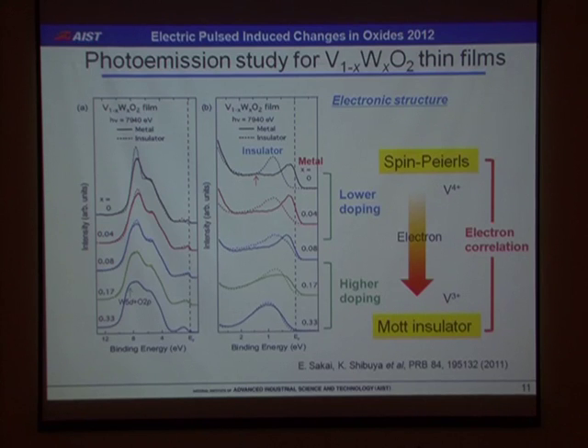And the electronic structure is investigated by photoemission spectroscopy. Here, around 5 electron volts, there is a shoulder, mainly contributed from the hybridization between tungsten 5d and oxygen 2p orbitals. This is the near-EF spectra, and in the lower doping region, the typical behavior of a sharp Fermi edge and sharp spectra around EF, and a satellite peak at about 1.4 electron volts, was seen. And in the insulating phase, a single peak at about 0.8 was seen.